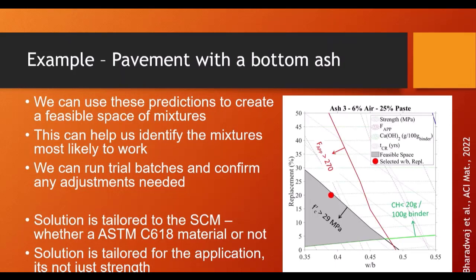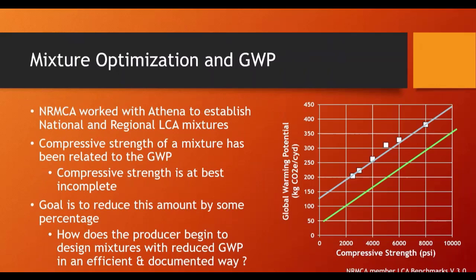And if you overlap all those graphs together with the region of feasible mixtures, what you see is that gray blob starts to appear. That gray blob is all the mixture compositions that you could be using with a high potential for meeting your specified values. So all of a sudden now, we have a great spot to start looking for mixture solutions, right? We can all of a sudden start to say, this is the place where we would try to design our mixture. And we can go through and we can do things like the global warming potential, all right?